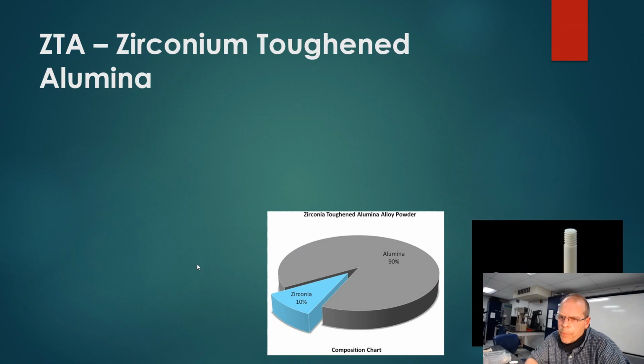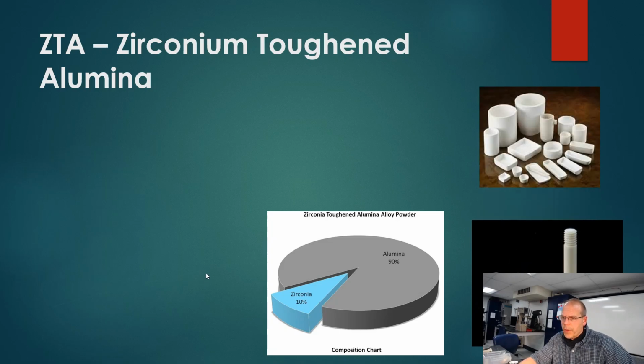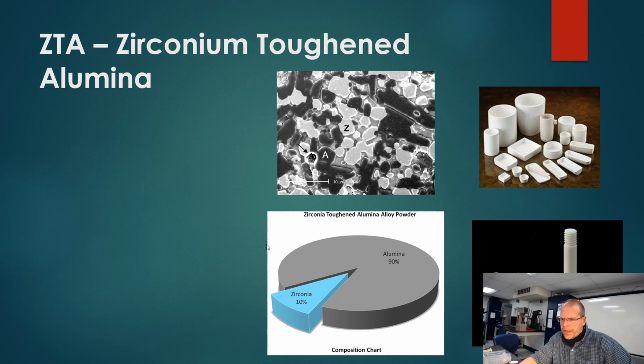The ceramic composite that we're going to be making is a substance called ZTA, which is known as zirconium toughened alumina. And zirconium toughened alumina is just that. It's alumina, which we're going to stick a little bit of zirconium oxide in and try to make tougher. Again, you can see an SEM picture. What you're looking at in the darker images are particles of alumina, and the lighter images are your zirconium. You still see some porosity involved here. But the cool thing about zirconium oxide is that by adding it to alumina, you actually make it 20 to 30% tougher. High strength, fracture toughness, increased hardness, more wear resistance. There are many features that are very positive when you do this.